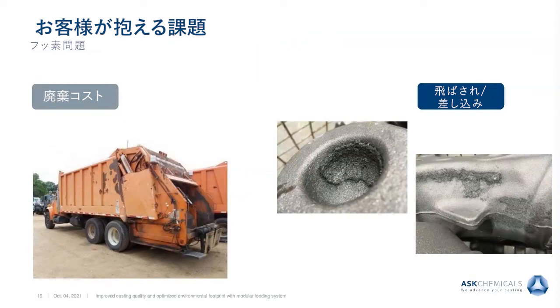And during the last years, we very often made the experience that by using our fluorine-free formulations, it's possible to avoid or to remarkably reduce the possibility of explosions and penetrations. We have had several customers where we switched from standard formulations from our competitors to our fluorine-free formulations, and we reduced the scrap and the rework remarkably.